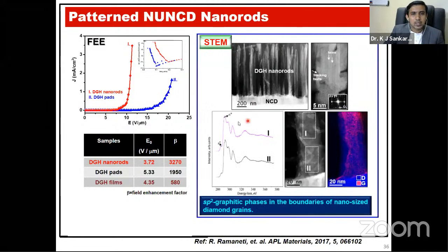So to know the reason, again we carry out TEM. This is another advanced version of TEM called scanning transmission electron microscopy, in which we can look at a single NUNCD nanorod. From here, we took only one nanorod, and the blue region shows the diamond, and the red region shows the graphite. The presence of graphite in the nanorods gives very good electron conduction, so that it can achieve a very low turn-on field. So sp2 graphitic phases in the boundaries of the nano-sized diamond grains achieve very good field electron emission with high aspect ratio.